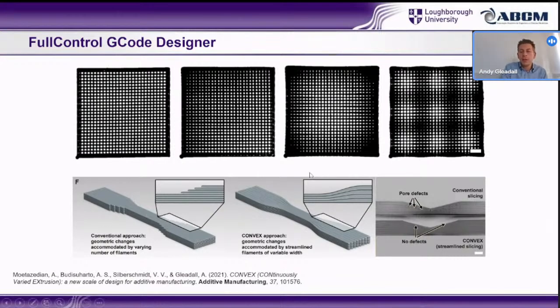And that then ruins your test, because you're testing the strength of the defects in a part rather than the actual material. Whereas on the right, with this idea of constantly varying the extrusion width, we can go from wide to narrow in terms of the overall geometry and the individual filaments to get really good continuous deposition and good quality. And that has enabled us to do loads and loads of mechanical research, which I'll talk about a bit later in this talk.